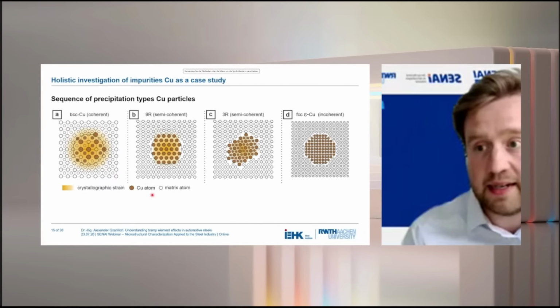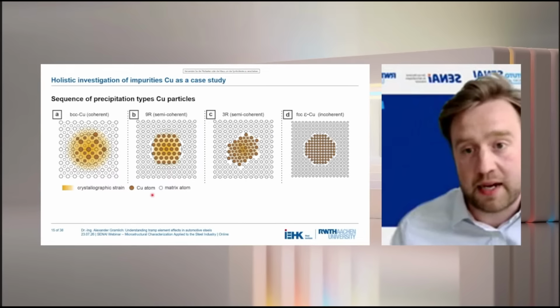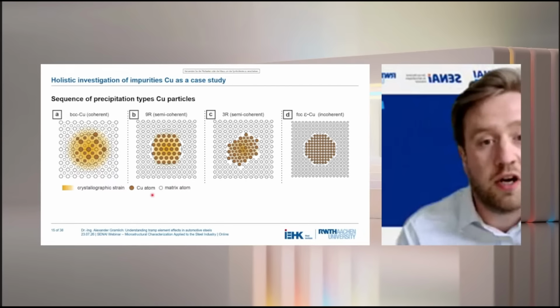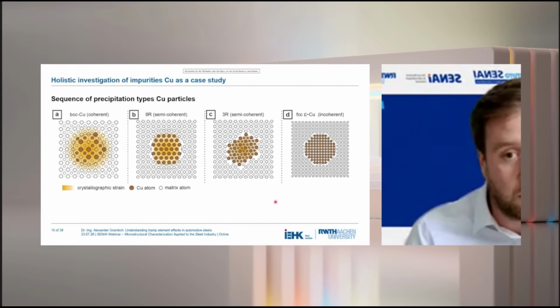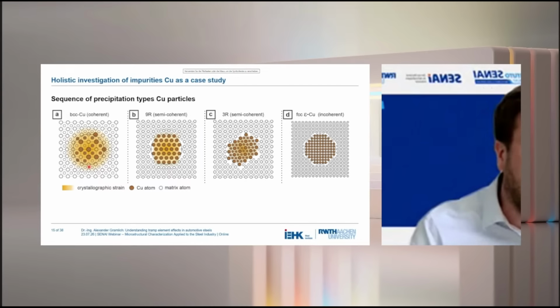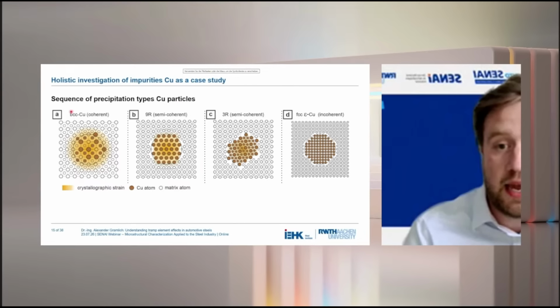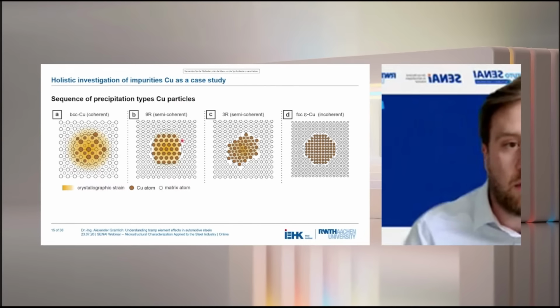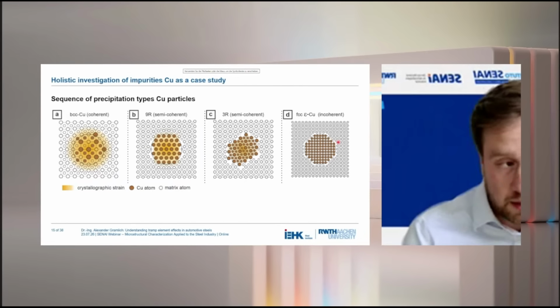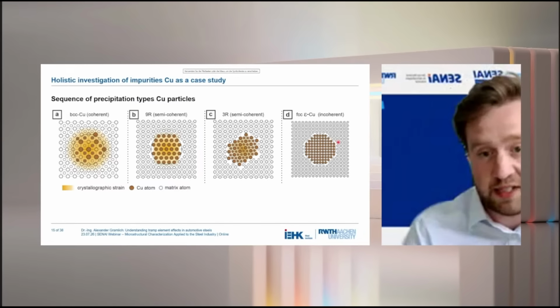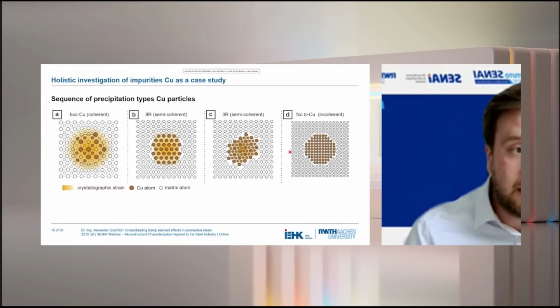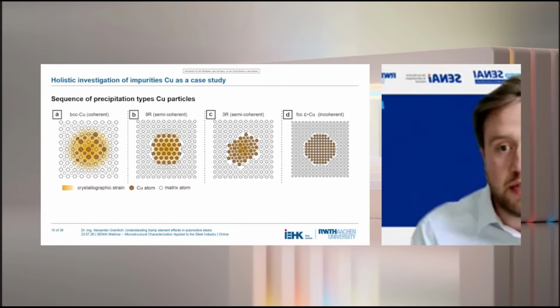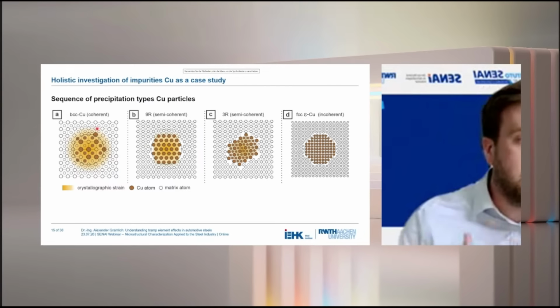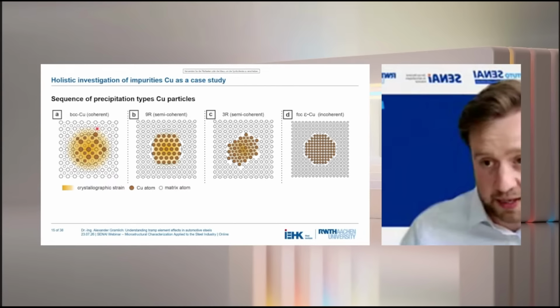As I already said, quite an extensive amount of research has been done in the past. And this is the current opinion in the literature, how the precipitation process goes on. So you start with a very high amount of iron still in your copper precipitate, and you have a coherent BCC precipitate, which over time develops over two semi-coherent intermediate states into the FCC, thermodynamically stable, incoherent copper precipitate. As indicated by the crystallographic strain, the FCC one has basically not much influence, and the BCC one is the most interesting one from a mechanical engineering perspective.